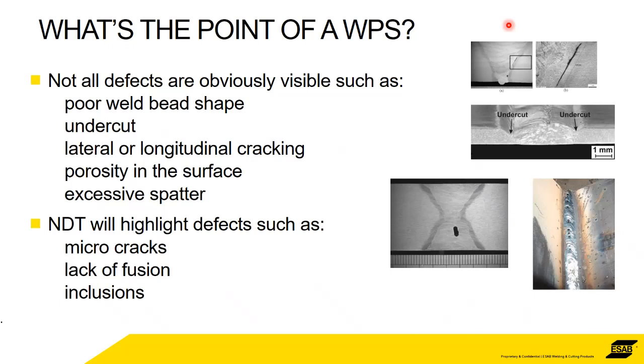So anybody that can weld can tell a good weld straight away, or rather you can tell a bad weld just by visual inspection. You can see if there are excessive amounts of spatter, or if the bead shape itself looks terrible. You can see porosity if it's in the surface, and then cracks as well, obvious signs of a poor weld.